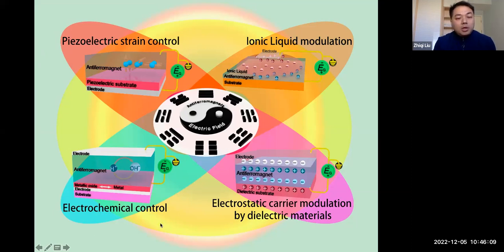We can also have electrochemical control, which I did not mention in this talk, but it could be really obvious. For example, if you have an ultrathin cobalt layer, you make a dielectric layer like aluminum oxide on top of it. If you apply an electric field, you can drive the migration of oxygen ions that can oxidize or deoxidize cobalt. You get either cobalt or cobalt oxide. So you will have a ferromagnetic metal or an antiferromagnetic insulator. And the last one is electrostatic carrier modulation by dielectric materials, for example, strontium titanium oxide.